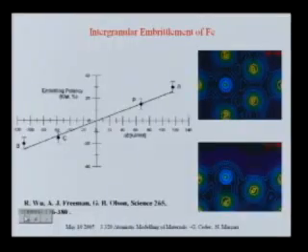But there's another effect, I think, which has to do with bonding potency. In a grain boundary, they have higher coordination. So they gain a lot more from covalent bonding than these two. These two don't gain as much from being coordinated by iron atoms. I think that's the gist of it as I remember, but that's exactly what that paper is about.